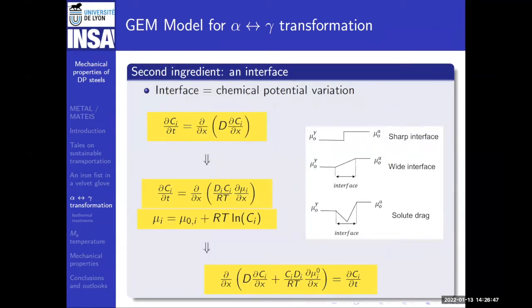Second ingredient: remember, we want to model the transformation of ferrite into austenite. So we have a moving interface, and we want both phases to be described with an interface. If you have an interface, you cannot use this classical Fick equation. You have to transform it into an equation where the diffusion is a function of the chemical potential and not only the concentration. So we have to slightly transform the diffusion equation, and let's say that the interface is seen as a chemical potential variation.